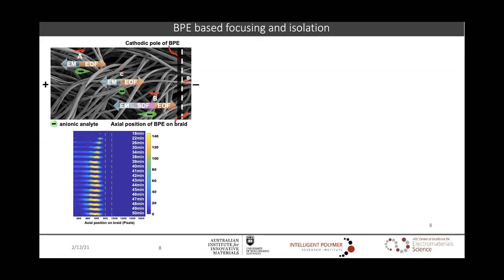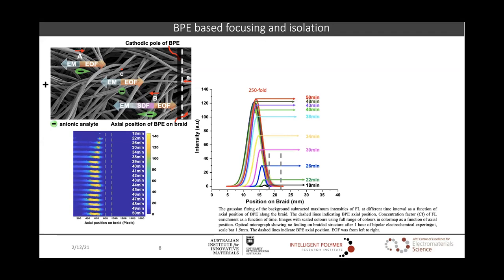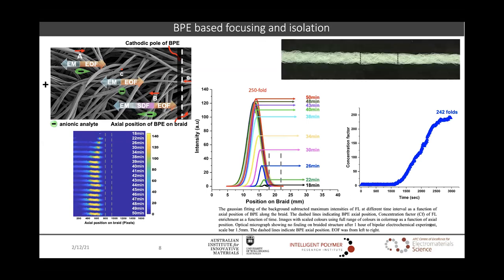And here, with Gaussian fitting of the peak intensity data, you can see that not only did the fluorescein remain focused, but its intensity kept increasing with time. That means the concentration kept increasing, and we were able to achieve up to 250 folds of concentration enrichment. And in this picture, you can see that no fouling was observed on the textile-based construct even after running the high voltage electric field for 1 hour. So the system was quite robust as well.